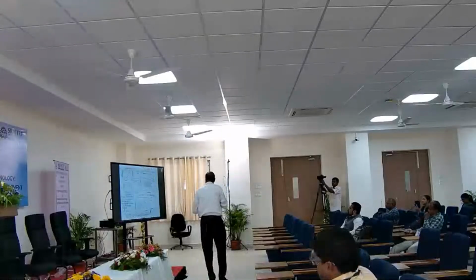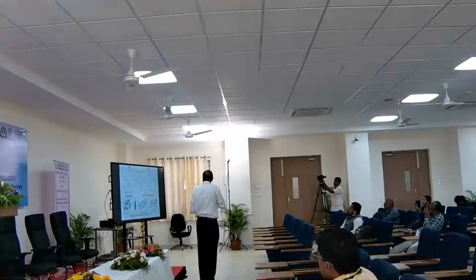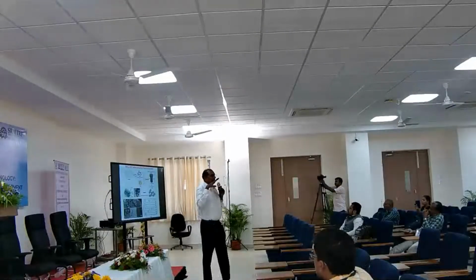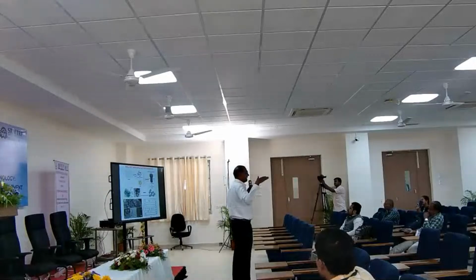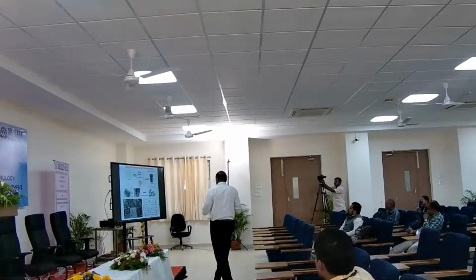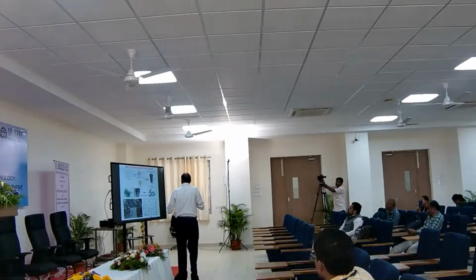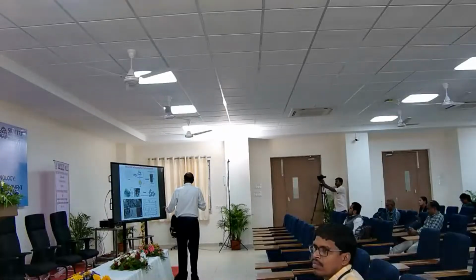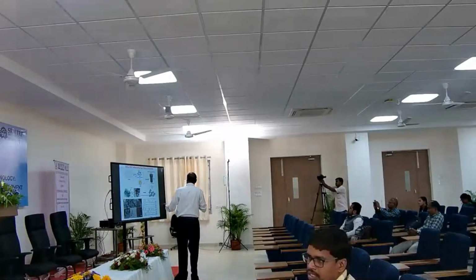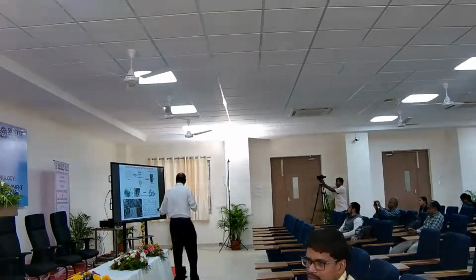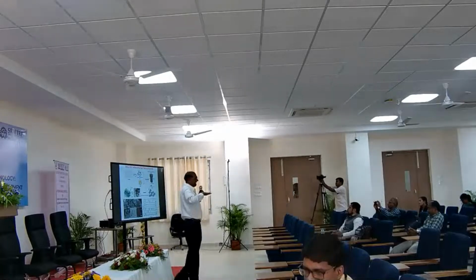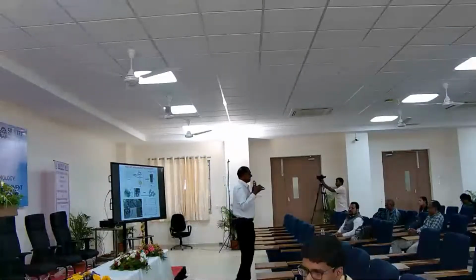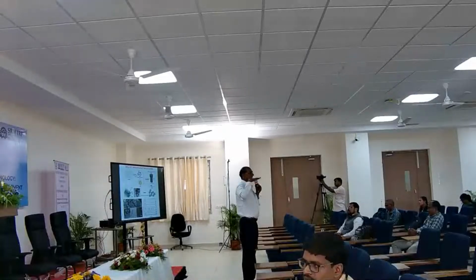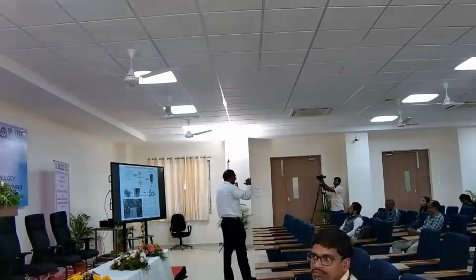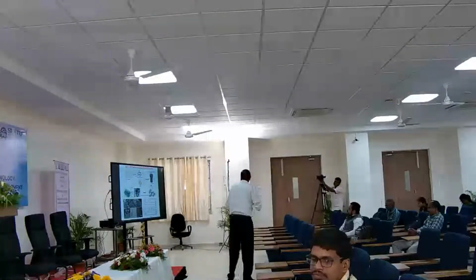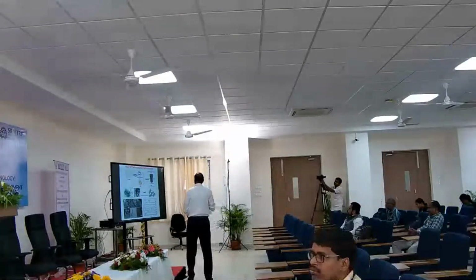This is actually the heterostructure, for example making two 2D layers. One is MoS2, another one is RGO. If you make a composite like this, you get this kind of layer structure, only graphene, molybdenum disulfide, graphene alternate layers, and the TEM shows that stacking of layers. This kind of heterostructure has a lot of interest, where we look into the interface stability.